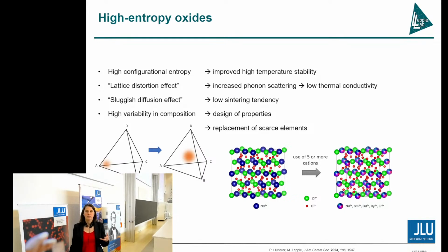And these properties are thought to be introduced by a high configurational entropy, which we achieve by mixing multiple elements in equimolar amounts. And this high configurational entropy would then lead to an improved high temperature stability just by the Gibbs equation. Also, we would have high lattice distortion effects, and lattice distortions increase the phonon scattering, and thereby we have low thermal conductivity. There's also a sluggish diffusion effect, which leads to a low sintering tendency, which is important at these high temperatures. And since we have a high variability in composition, we can actually design special properties to the needs, and also we can replace scarce elements.